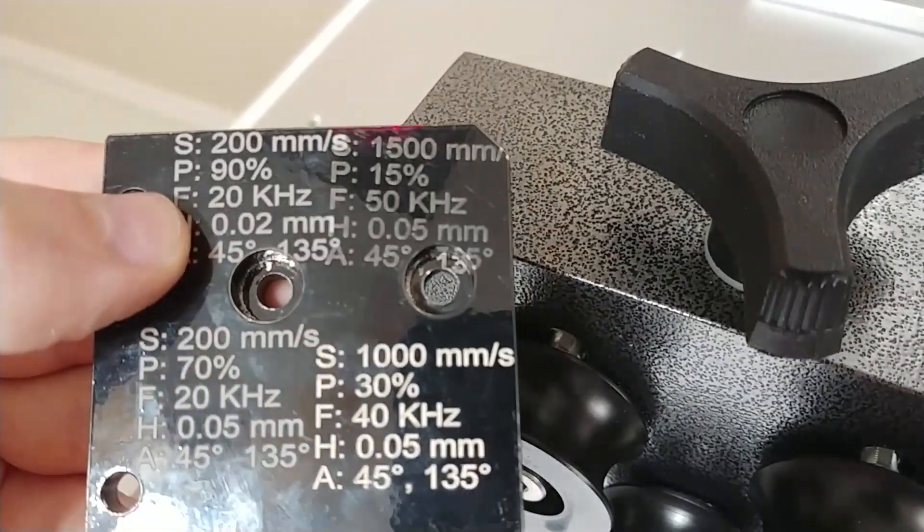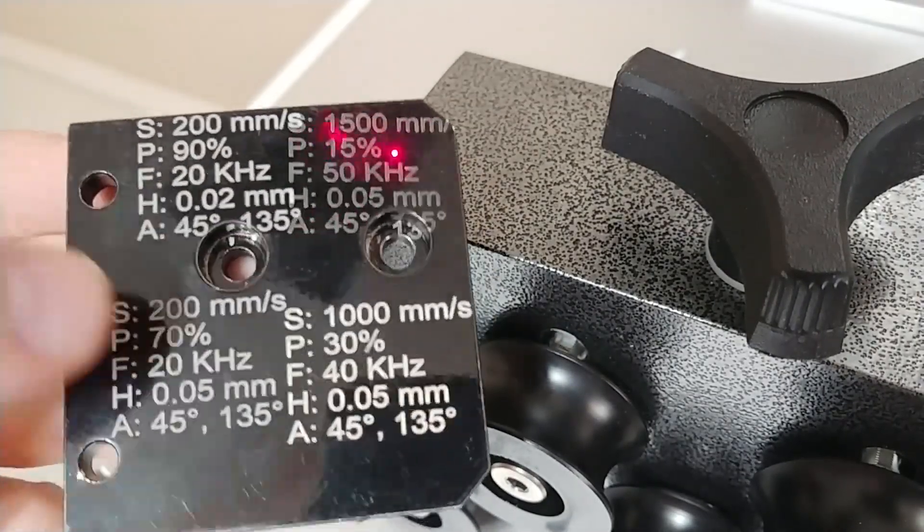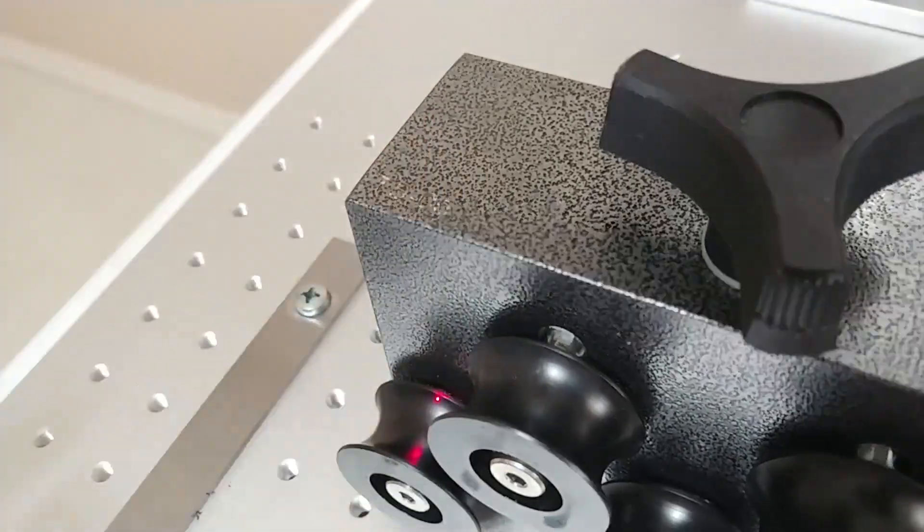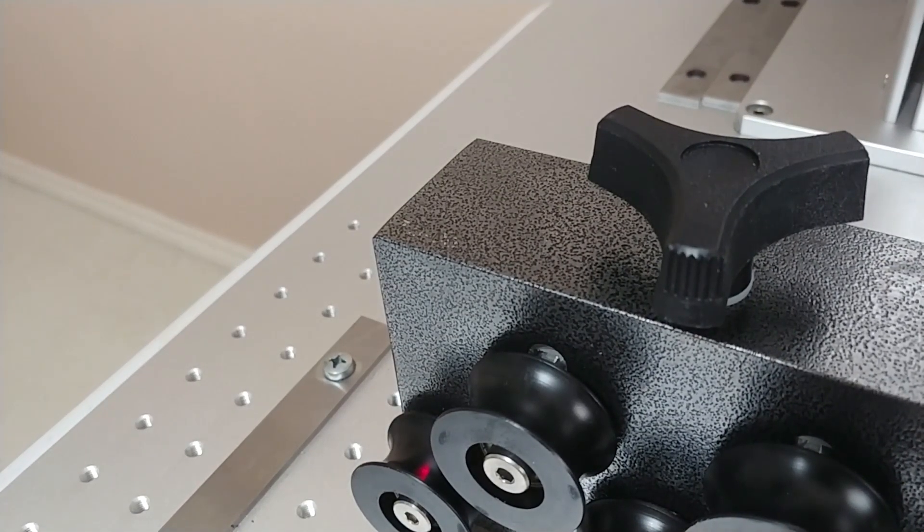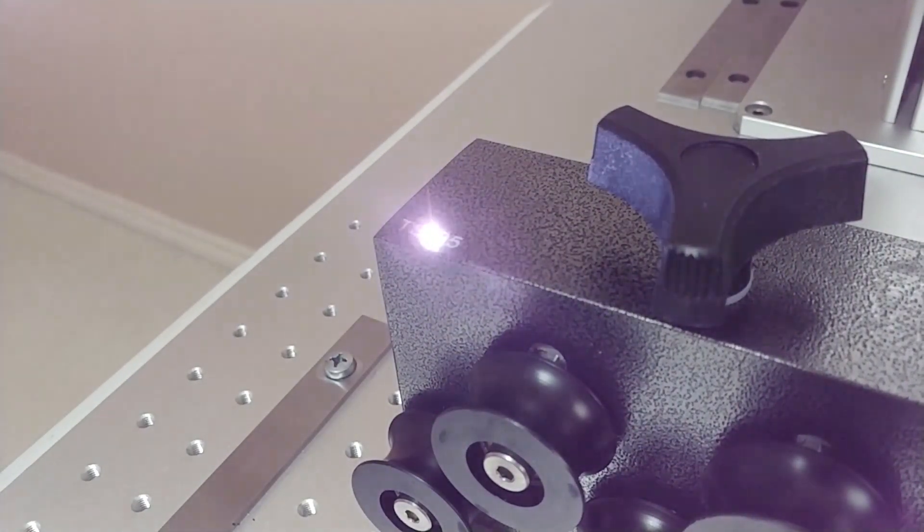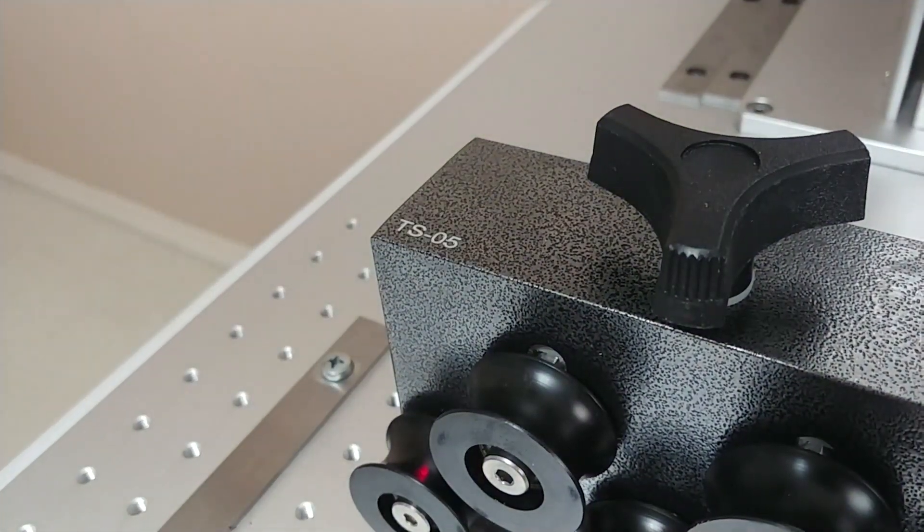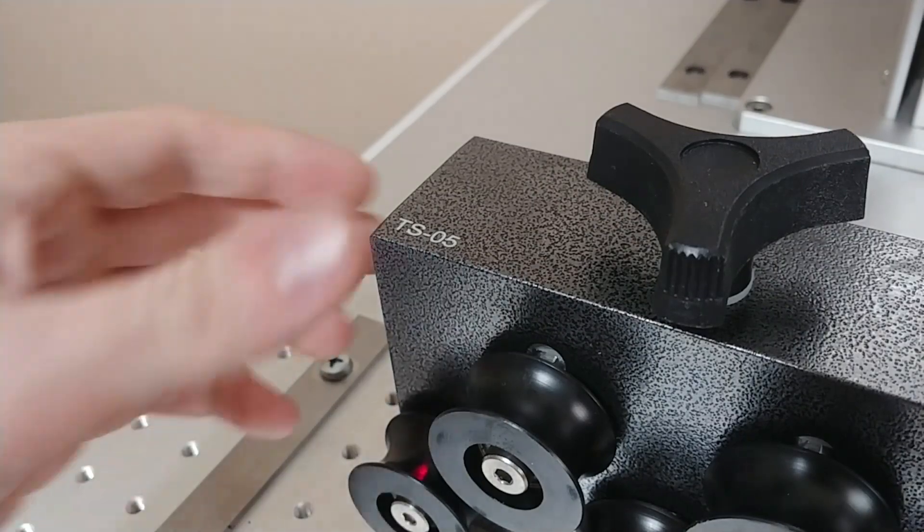So I'm going to up the power and do the exact same thing and go right over it. So instead of 30 I'm going to go back to this 70. Well that definitely got through the powder coat and that looks pretty good.